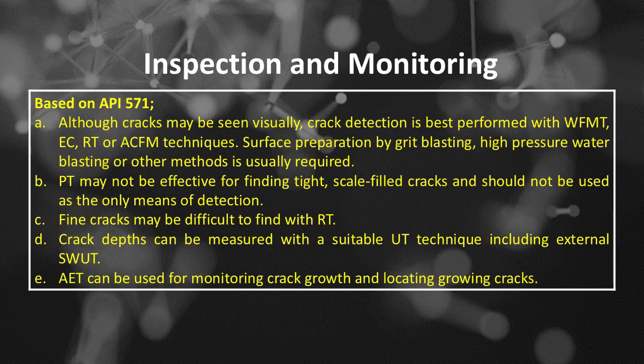Caustic stress corrosion cracking or caustic embrittlement prevention and mitigation based on API 571, number A. Although cracks may be seen visually, crack detection is best performed with WFMT, EC, RT, or ACFM techniques. Surface preparation by grit blasting, high-pressure water blasting or other methods is usually required. Number B, PT may not be effective for finding tight, scale-filled cracks and should not be used as the only means of detection. Number C, fine cracks may be difficult to find with RT.